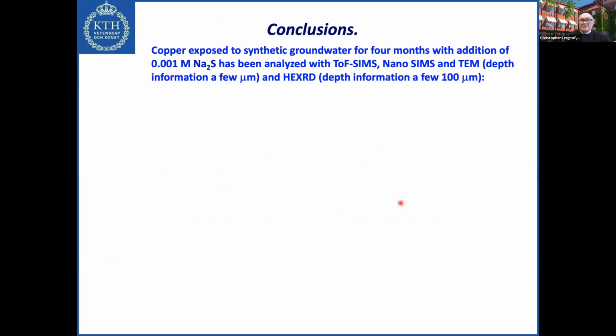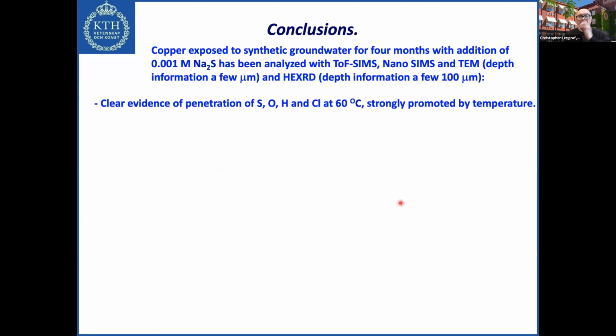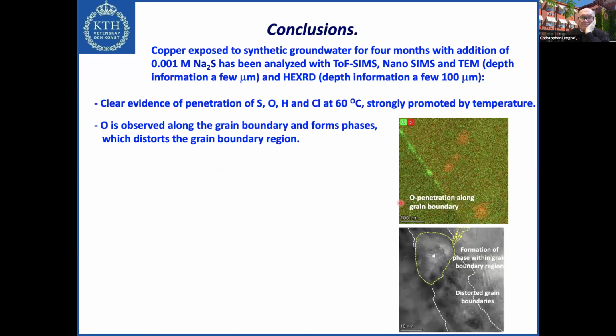So the conclusions so far: copper exposed to synthetic groundwater for 4 months with addition of 0.001 molar sodium sulfide has been analyzed with time-of-flight SIMS, nano-SIMS, TEM, and high energy XRD, which goes to a deeper depth, to a few hundred micrometers, the last technique. There's really clear evidence of penetration of these elements at 60 degrees, which is strongly promoted by temperature.